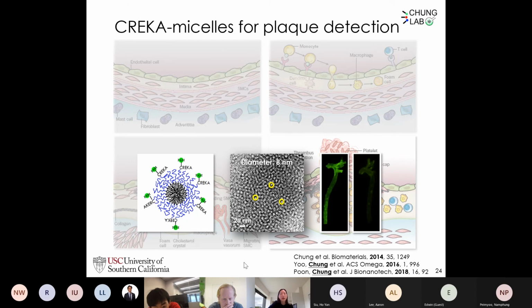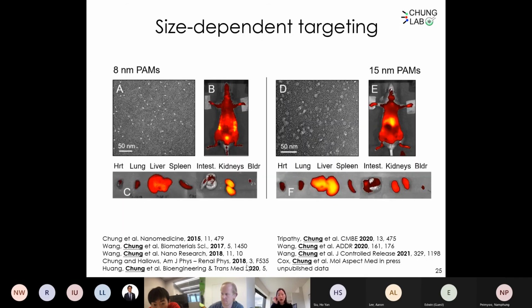And I was trying to understand their pharmacokinetic properties, their distribution and half-life as a function of concentration effects, really trying to understand toxicity, hemocompatibility, kind of doing that extra toxicology studies. But one thing that I saw really interesting with these micelles was that at certain concentrations, they would get to the kidneys really well. That's compared to a lot of the other types of micelles and other particles out there that get into the liver via the RES system, although our micelles also can penetrate the kidneys as well. But you can see that when they're smaller, they really get skewed towards the kidney side.